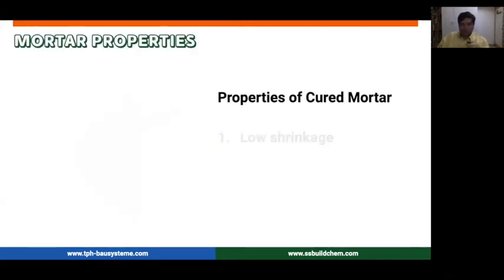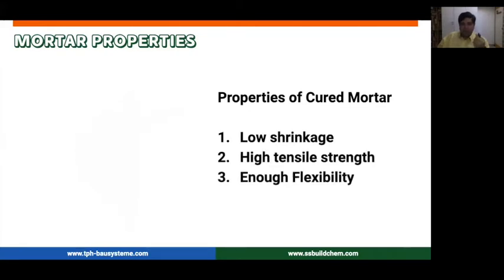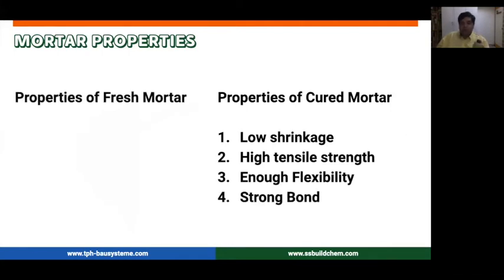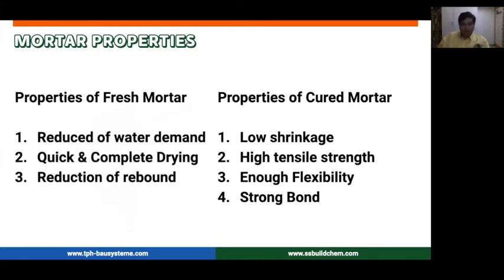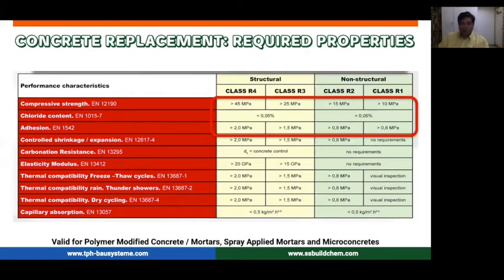When we look at what we need, our mortars should have low shrinkage, high tensile strength, enough flexibility, as well as strong bonds to the substrate. In fresh mortar, you're looking for reduced water demand, quick and complete drying, reduction of rebound if you're using spray mortars, and again, good bond strengths. That means you should be able to work with it very easily on the structure, and at the same time, it should give you the required mechanical protection as well. These are based on EN 1504. These are the basics that you need.